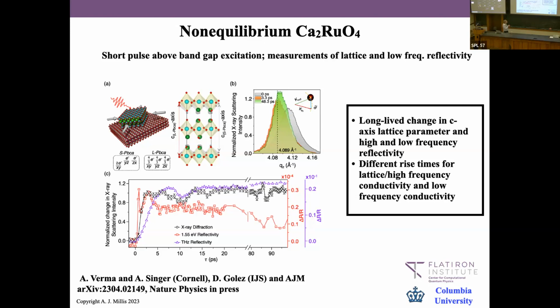The black thing is a change, which I'll come back to, in the lattice structure. And the purple thing, which is rather slower, is a change in the low frequency electronic structure, which is a reasonable proxy for is it metallic or not. This is one of these cases where you can't actually put wires on this non-equilibrium thing and measure its electrical resistance. So you have to use proxies like the low frequency reflectivity.